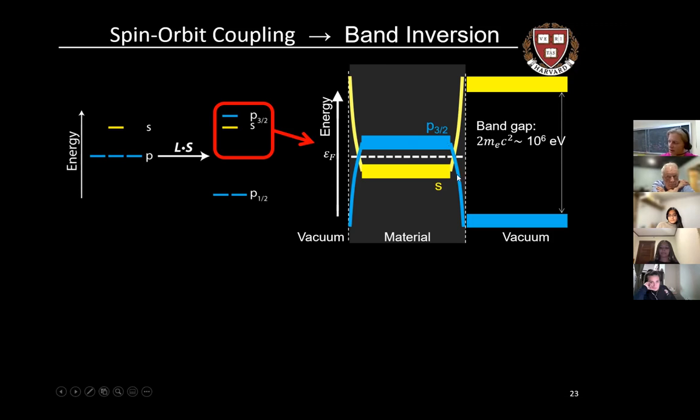If we put states in the gap, the states then cross the Fermi level, and at these boundaries this becomes a metal. And so that means that if we were to cut the material in half straight down the middle, we would still have to break the gap to make the interface with the adjacent material or vacuum that has a different band ordering. And so no matter how many times we break this thing, we're always going to have conducting states at the interface. This is a very cartoony conceptual understanding of what's going on.